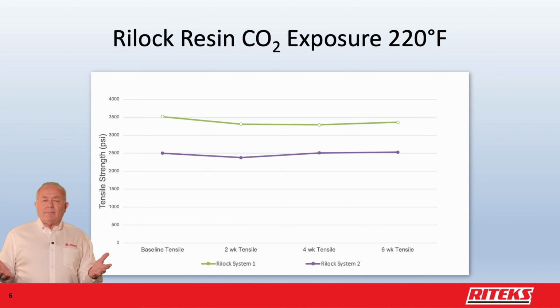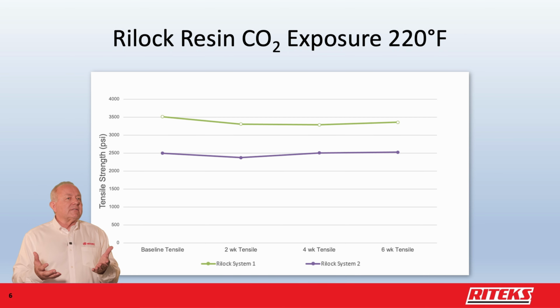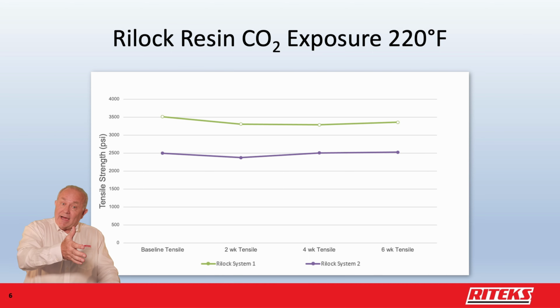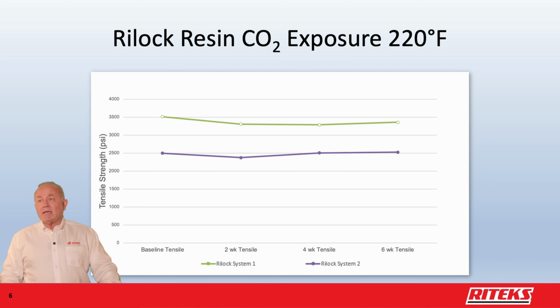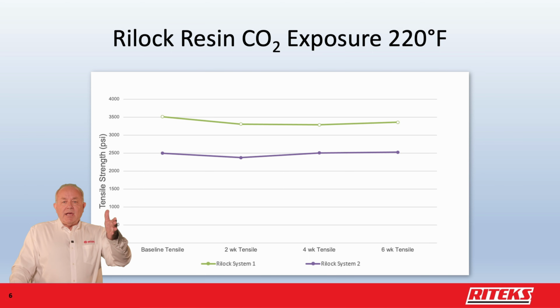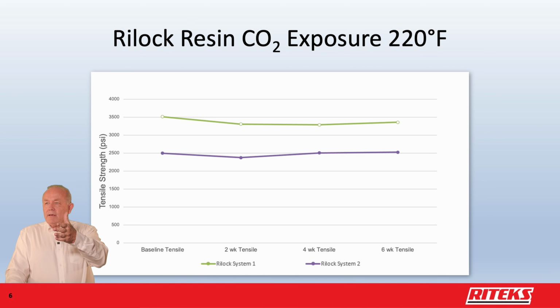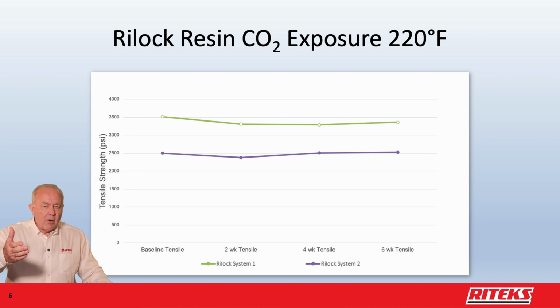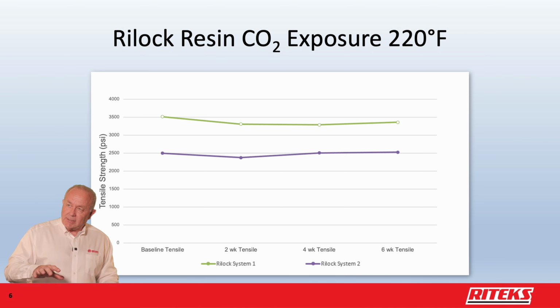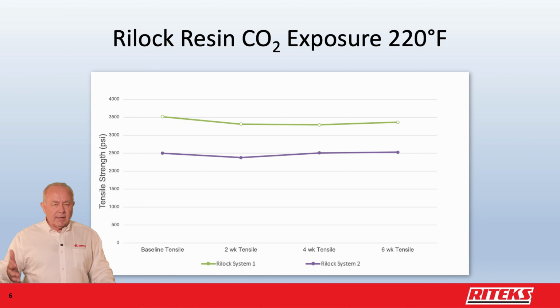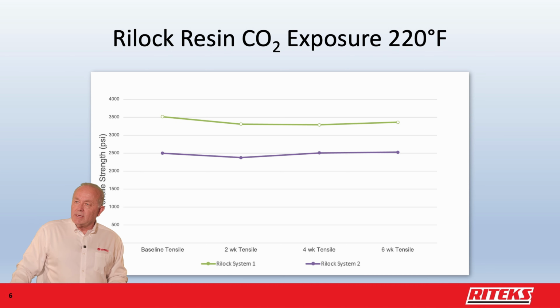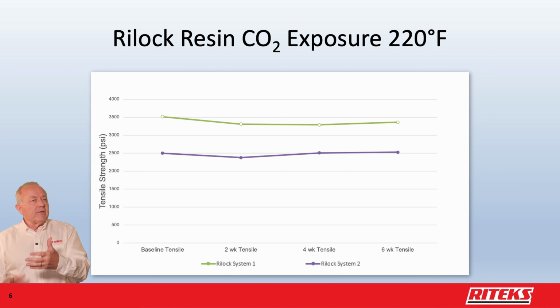Here's an example of the resistance of two different resin systems at 220 degrees. From the baseline, before we put them in exposure, up to 6 weeks at exposure. Look at the change in tensile strength, virtually none, over the 6 week period. In one case, we had over 3,000 PSI tensile, in the other case, over 2,500 PSI, with no drop in tensile strength over the exposure period.